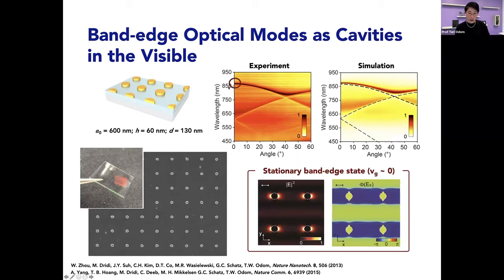And if we look at what's going on in the near field, right at this theta equals 0, or in the symmetry language, the gamma point of this lattice. Again, you can see these localized fields and this standing wave pattern. So we can control the short range and long range interactions.